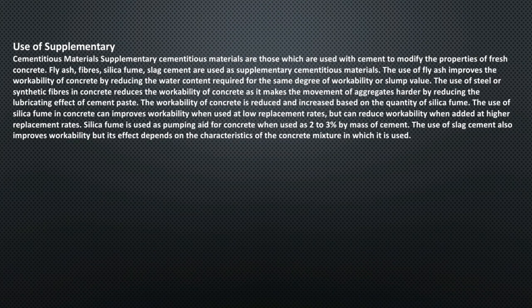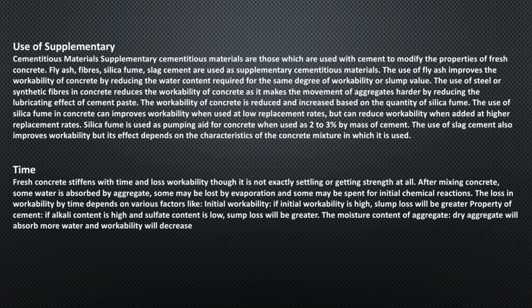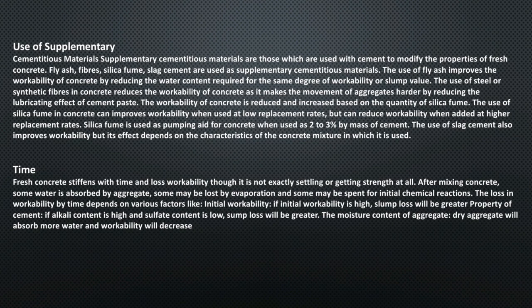Factor number twelve is time. Fresh concrete stiffens with time and loses workability. After mixing, some water is absorbed by aggregate, some is lost by evaporation, and some is used for initial chemical reactions. The loss in workability over time depends on factors such as initial workability — if initial workability is high, slump loss will be greater. If alkali content is high and sulfate content is low, slump loss will also be greater. Dry aggregate will absorb more water, causing workability to decrease.